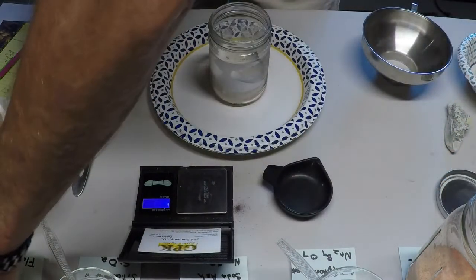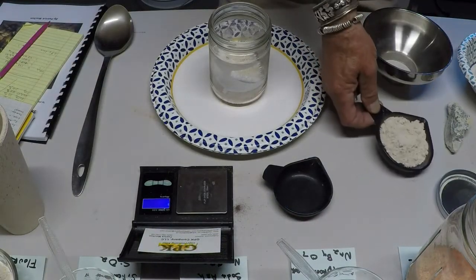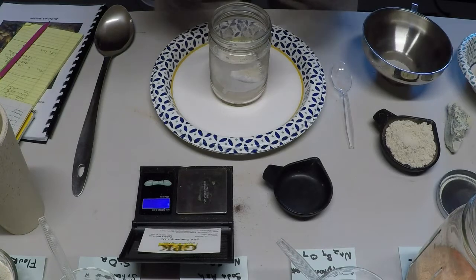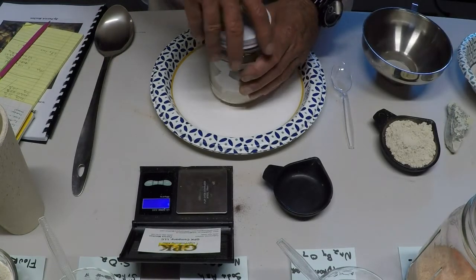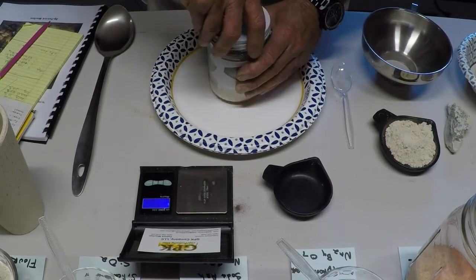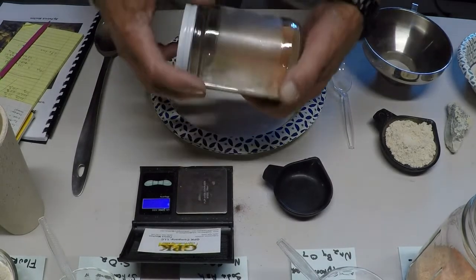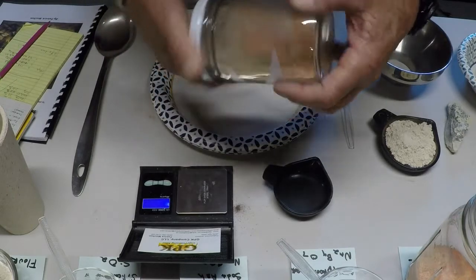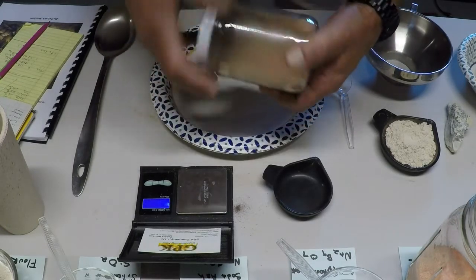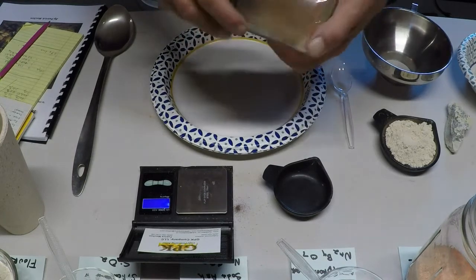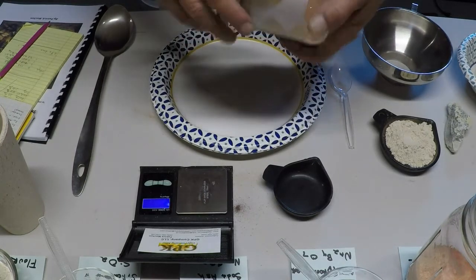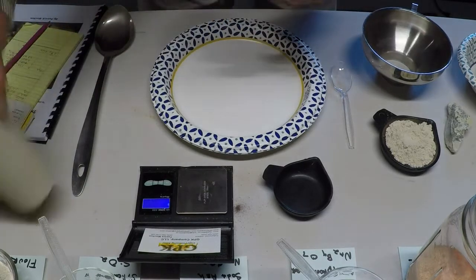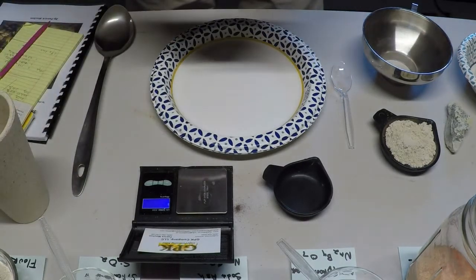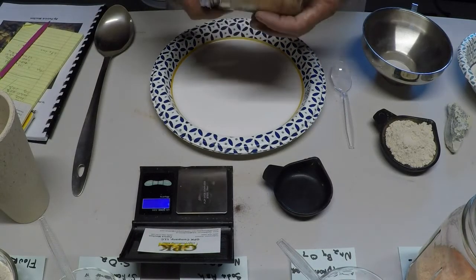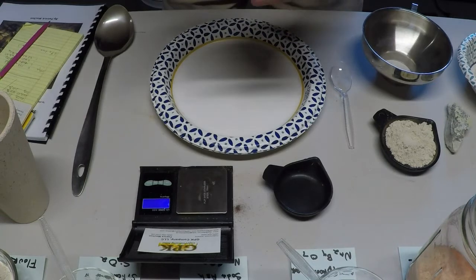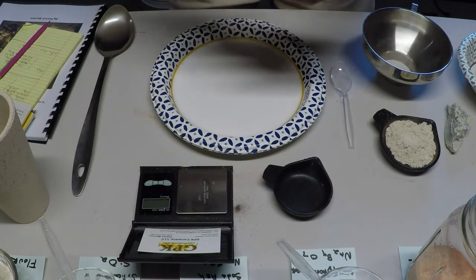And now that we have all of our flux components, we have 30 grams of ore in it, we'll put the lid on our jar, and then we mix everything thoroughly. And the best way to mix everything, as you can see the colors kind of showing up, is to roll your jar. And what that does is that distributes everything evenly and homogeneous in your crucible when you pour that into our crucible here. So we're just simply mixing them all together so that everything is homogeneous, and we put the heat to it.